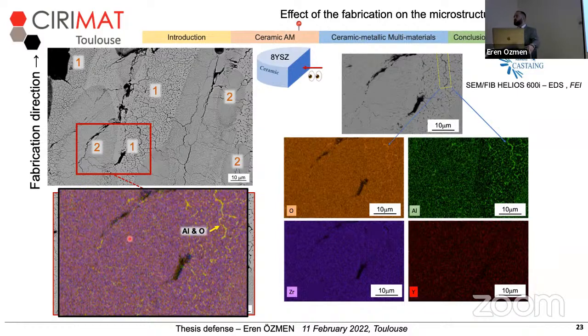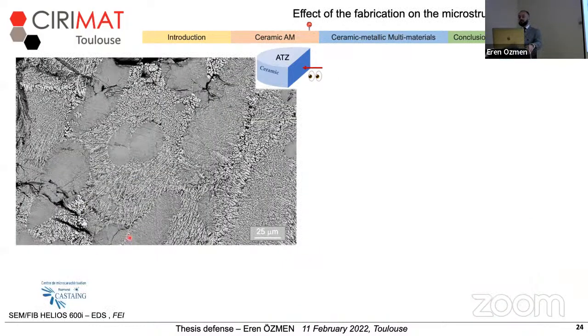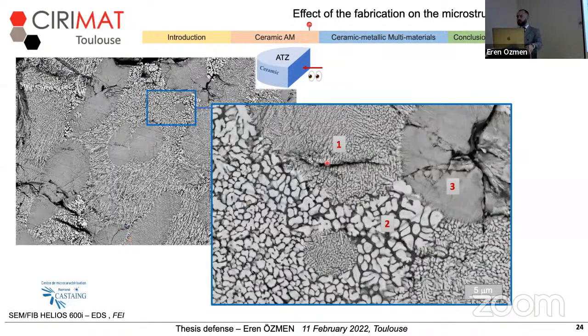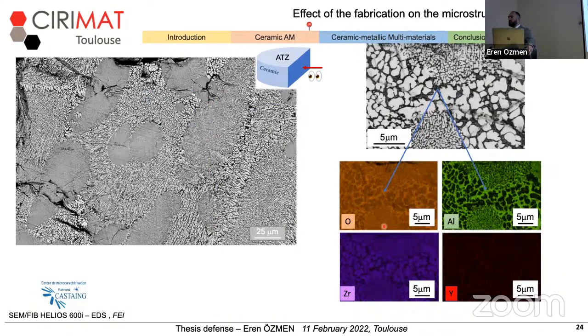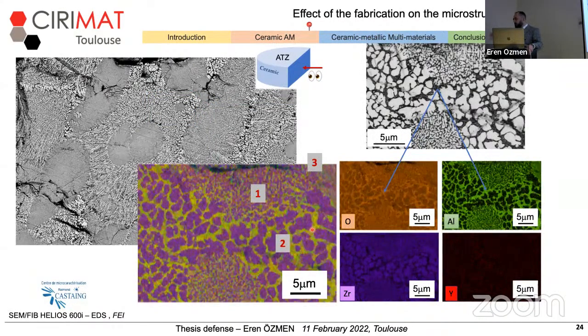What was unexpected here was to find aluminum and oxygen in some specific areas of this composition. When I checked ATZ, similarly, we identified three microstructures with fine, middle, and coarse grain sizes. And when I ran a similar elemental mapping, I figured out that the composition is still homogeneous. There is ATZ distributed everywhere. The only difference is the size of grains in these three microstructures. And the third part of the third question: the reason for these changes in the microstructure while they have the same chemical composition might be locally varying cooling rates and cooling speed.